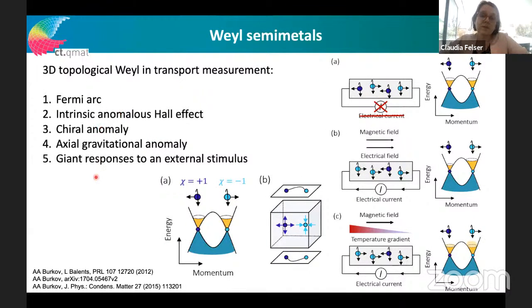If we want to investigate Weyl semimetals, we look first for the surface state which you see here. It's the so-called Fermi arc, which you saw in my first figure. You have these very special doubly degenerate Weyl points in the crystal at non-high-symmetry points, and on the surfaces the points are connected by Fermi arcs. So we have to find first the Fermi arc and the bulk electronic structure.